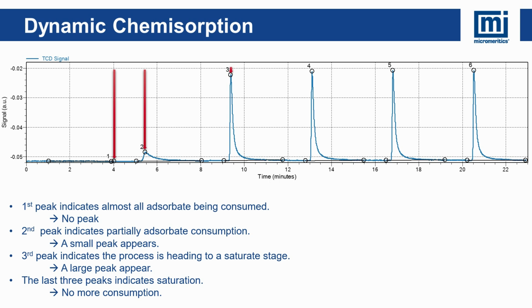Now let's look at the second injection. The second injection produces a small peak, which means that some probe gas is being detected by the thermal conductivity detector, TCD. This suggests that after the first pulse, a portion of the catalyst sites are still available for adsorption, but not all of them were fully saturated by the first injection. As a result, some hydrogen is still available in the system to elute and be detected.